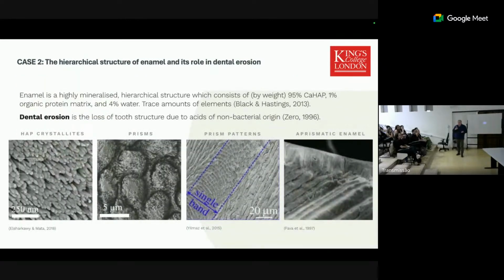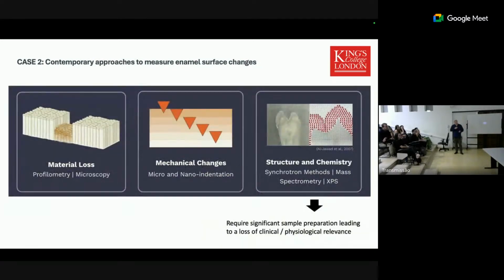So we took the case example of dental erosion. My clinical teams are very, very big into treating tooth wear at King's, and we understand some of the parameters that lead us to having progressive enamel loss. And what we know is that we can normally detect this using things like profilometry, where we measure how much of the surface gets removed. We can measure it with indentation, whether that's micro or nano. And we can measure in slices through the teeth the structure of the tooth.